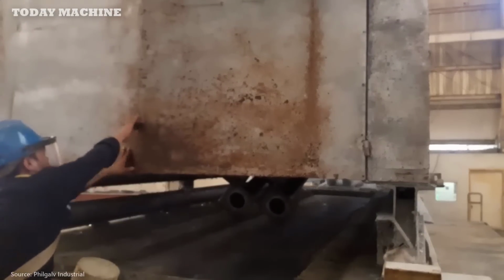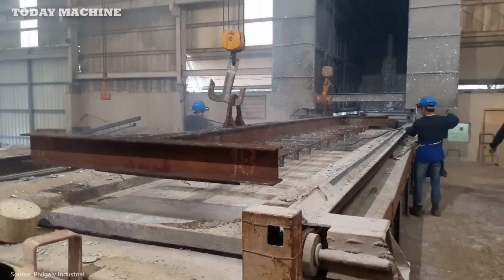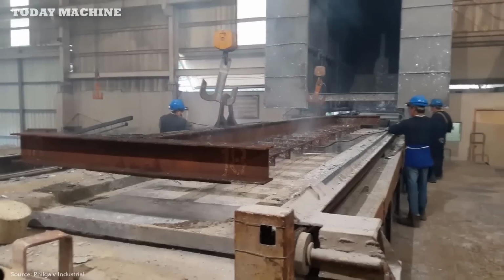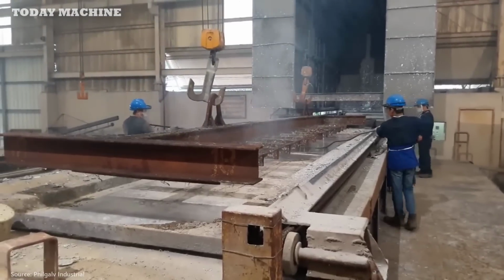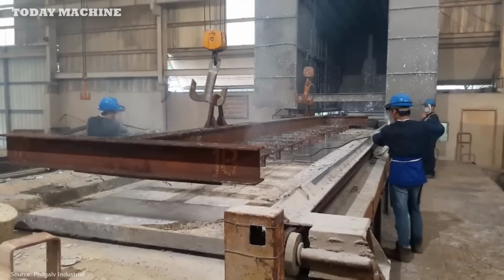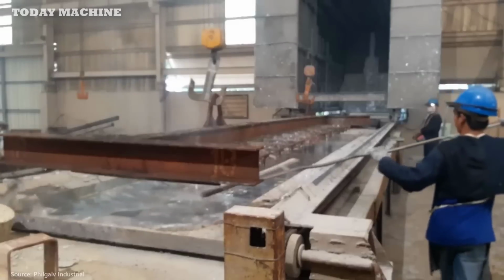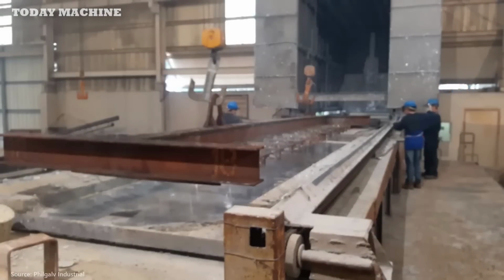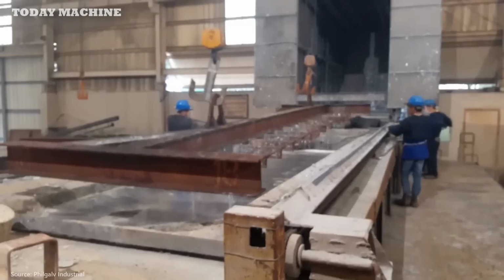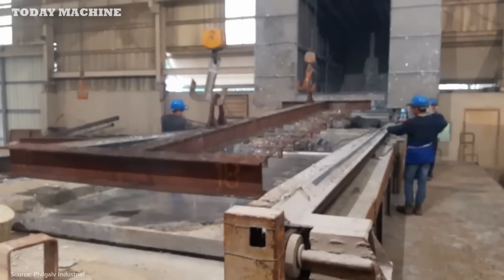Once prepared, the steel is dipped into a molten zinc bath, typically heated to around 450 degrees Celsius, 842 degrees Fahrenheit. During immersion, a metallurgical reaction occurs between the zinc and the iron in the steel, forming a series of zinc-iron alloy layers topped with a pure zinc outer layer.